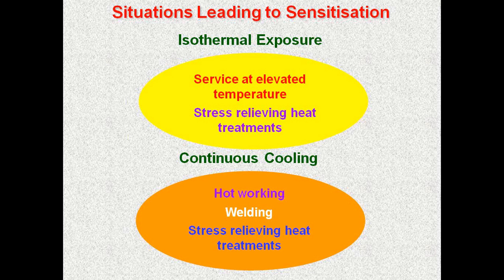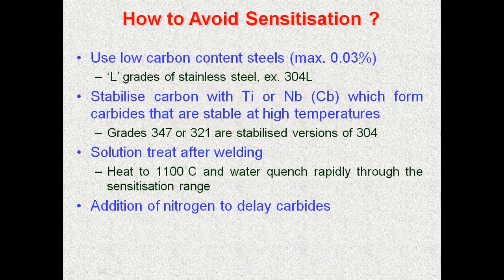You reduce the carbon content, because carbon forming carbide is the root cause of this problem. So reduce the carbon to less than 0.03%, and you can avoid carbide, you can avoid the formation of chromium depleted zone. Or you can use titanium and niobium added stainless steels, which are called 321 and 347, which will stabilize the titanium and niobium carbide and will not allow the chromium carbide to form and the subsequent chromium depleted zone.